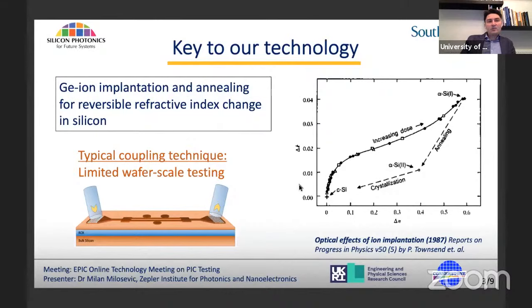So we use germanium ion implantation to create a refractive index change in silicon. As you can see here on the right, once germanium is implanted into silicon, it will cause crystalline lattice damage and increase the refractive index of the implanted material.